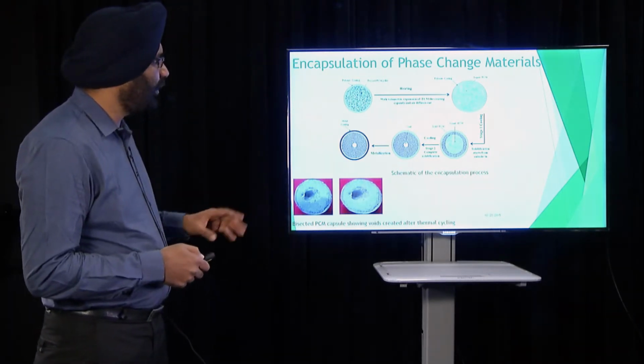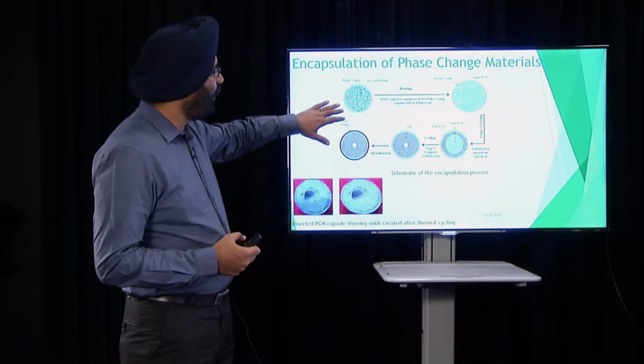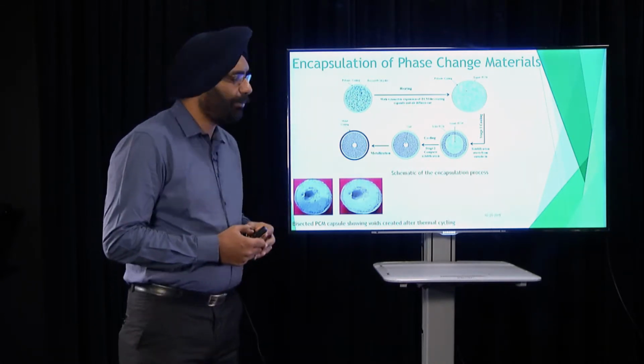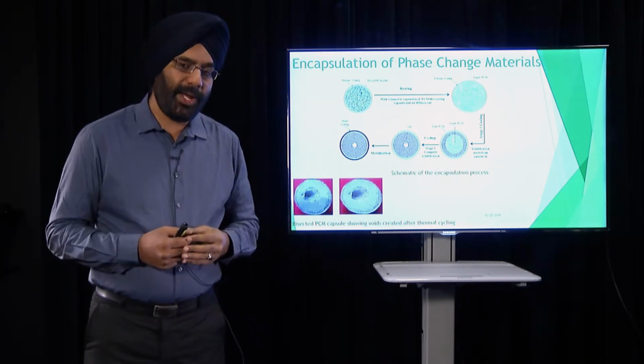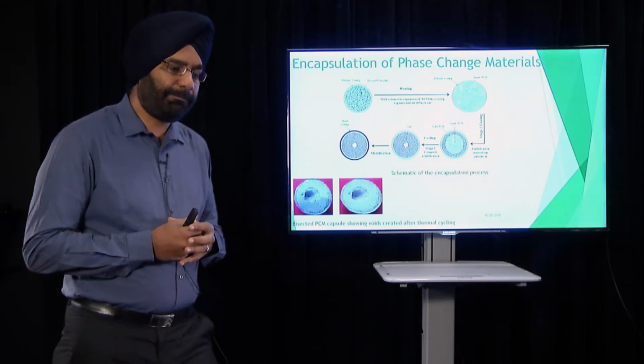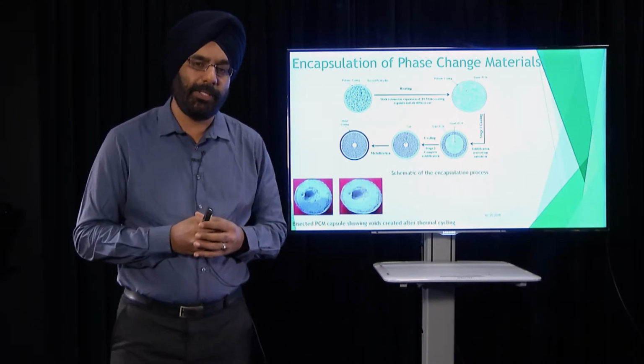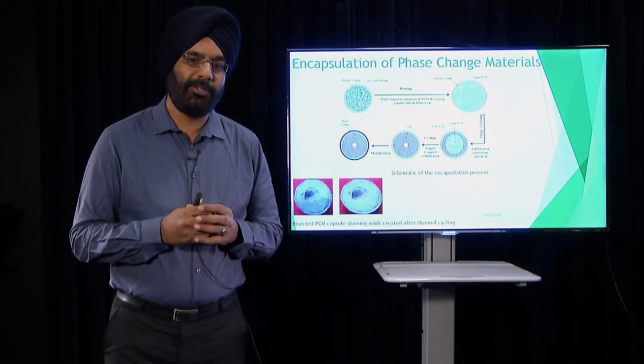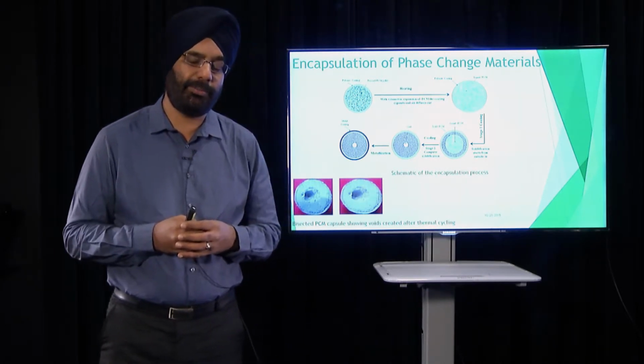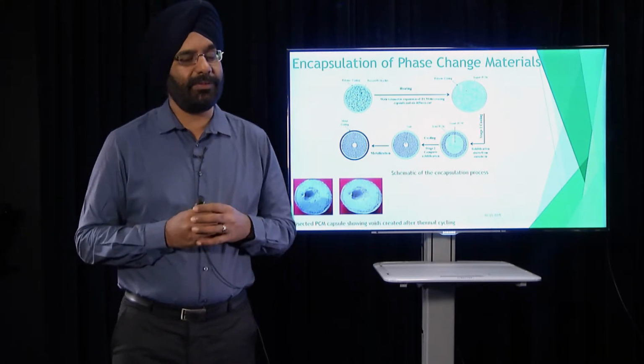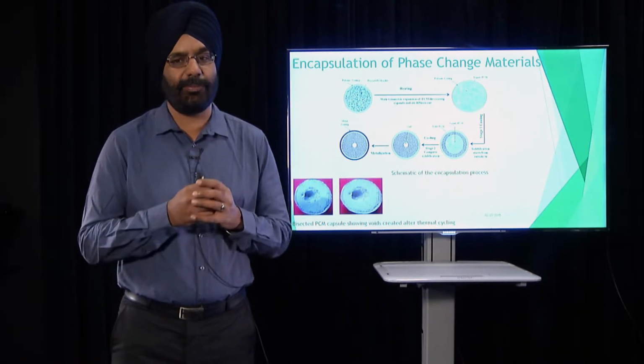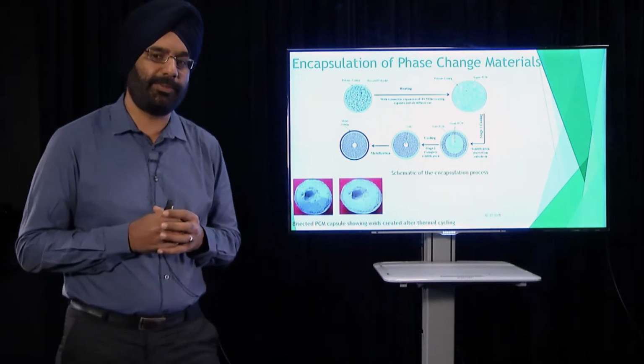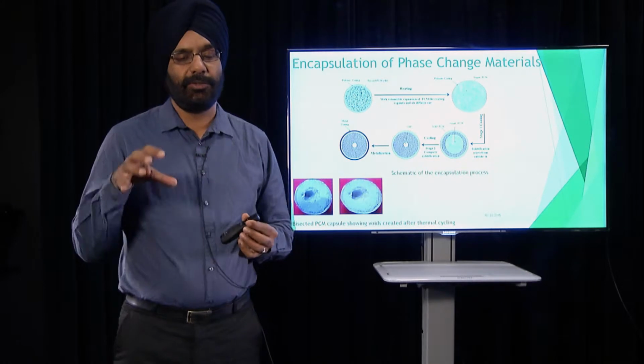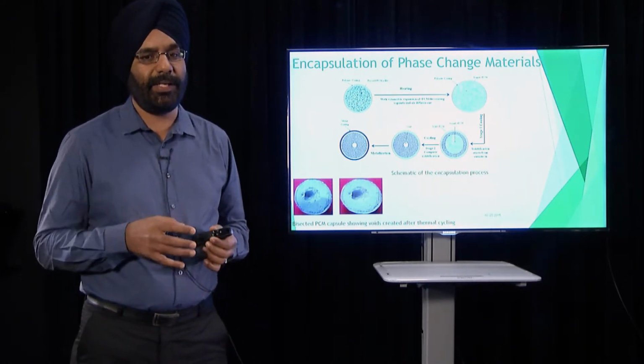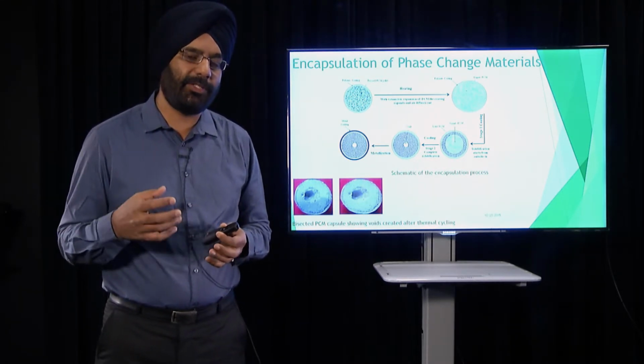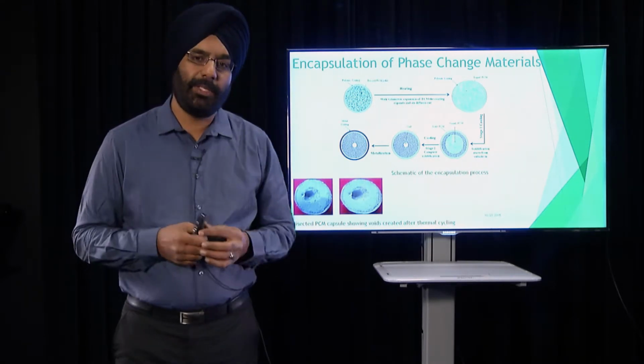The model developed to encapsulate this phase change material was that the PCM would be encapsulated with a polymer. The advantage of the polymer is that it can expand when you heat it up. A polymer is flexible in nature, so we wanted to choose a flexible polymer. As the phase change material expands and as the air inside the capsule expands, so does the polymer outside the phase change material. So having a flexible polymer outside solved our first problem of the physical barrier, what happens when the solid is converted into liquid, as you take a polymer which expands along with the material.